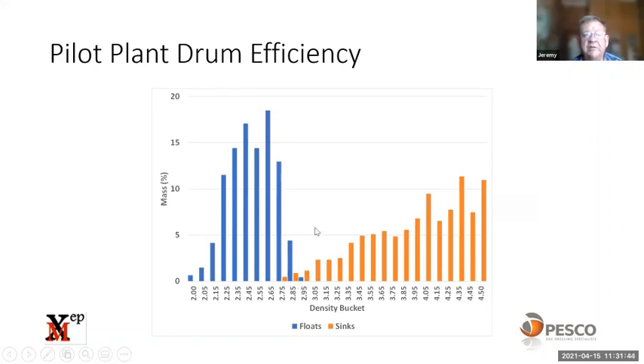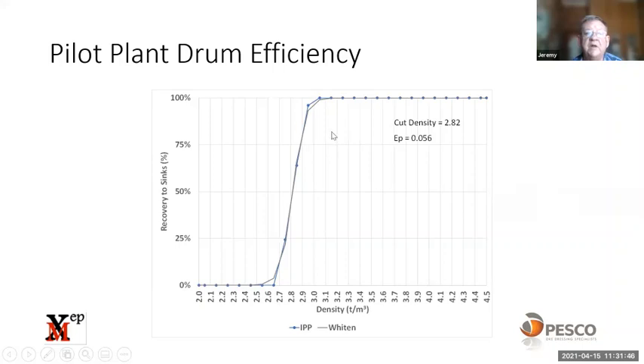If we take that further, we plot a partition curve. The blue dotted line shows the partition curve from the IPP data, and the gray line is the Whiten partition curve, which is fitted. So you can see the cut density was 2.82. We targeted 2.8, so that came out very close. And the EP was 0.056, which is a nice sharp separation.